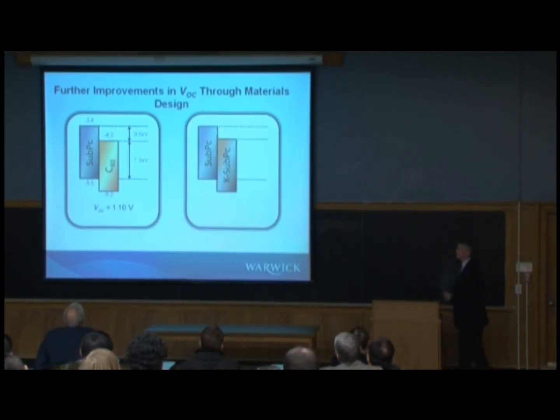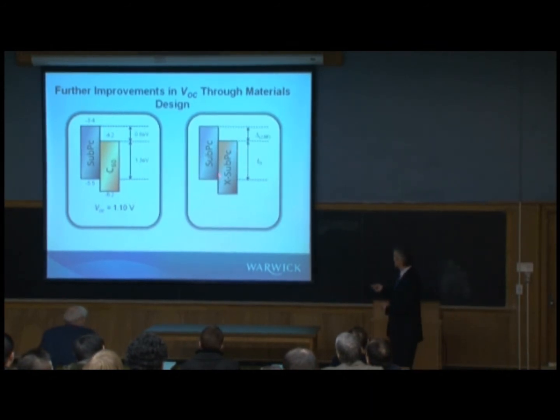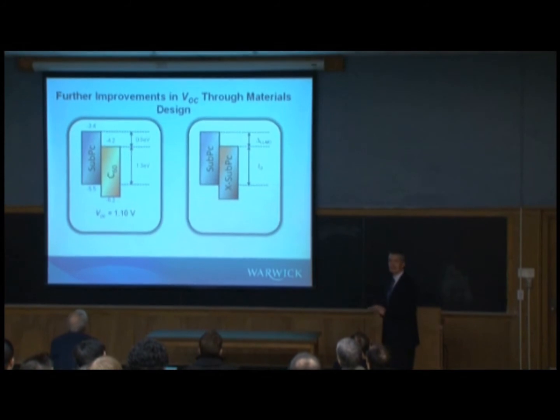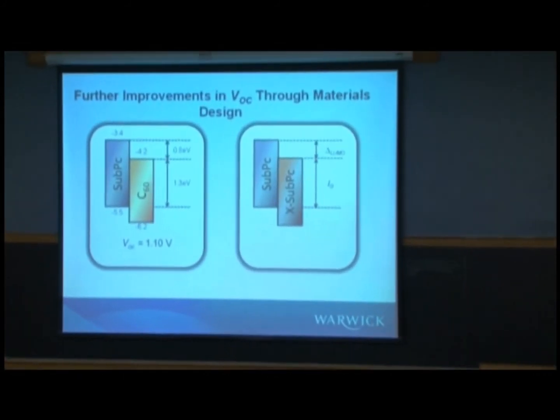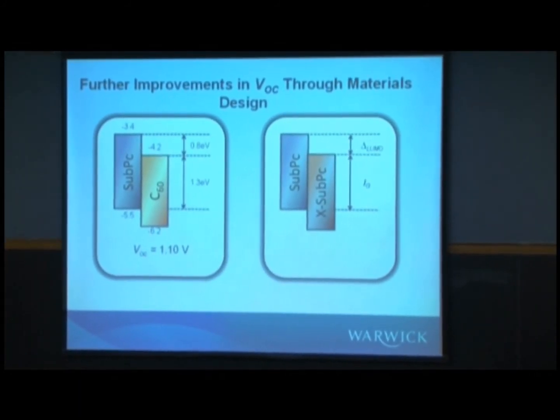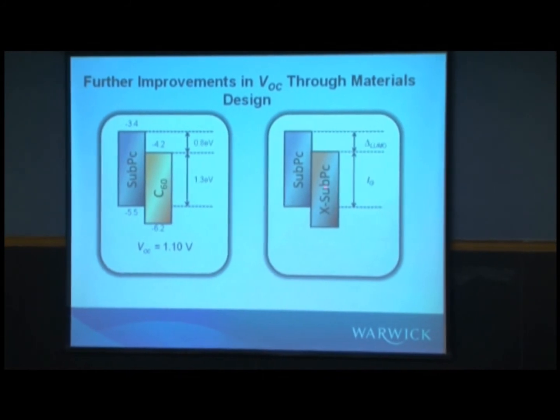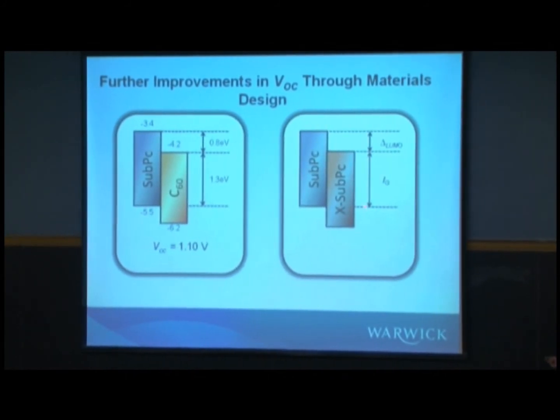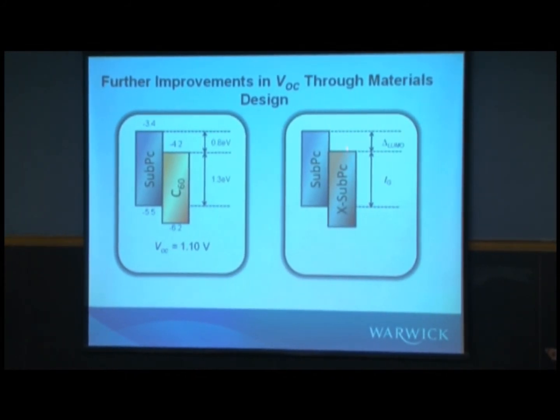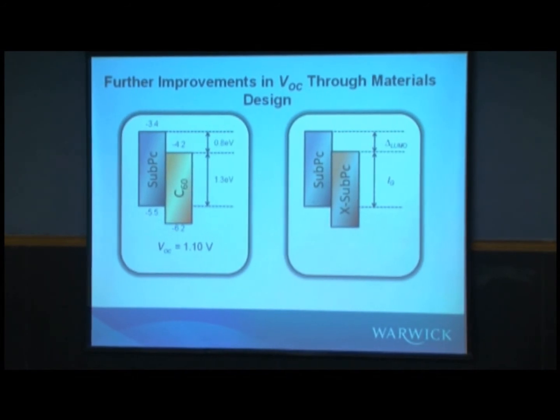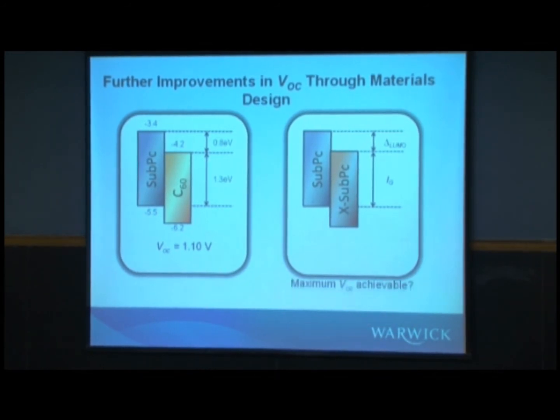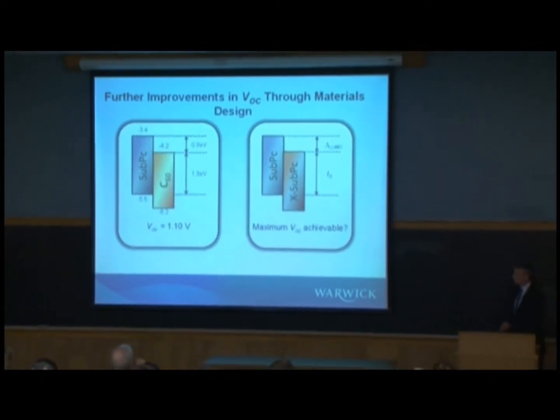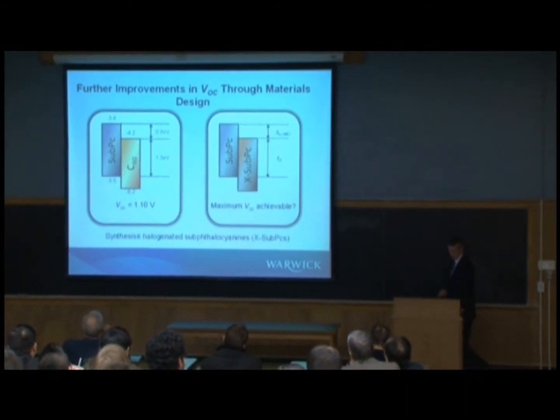If we now use a sub-PC donor with a halogenated sub-PC acceptor, we can drop those energy levels through synthesis, if we get the right material. In principle, we can enhance the interface gap whilst balancing the need for a sufficient energy offset in order to dissociate the exciton. So this requires some synthetic control of an existing molecule to see what voltage we can achieve.